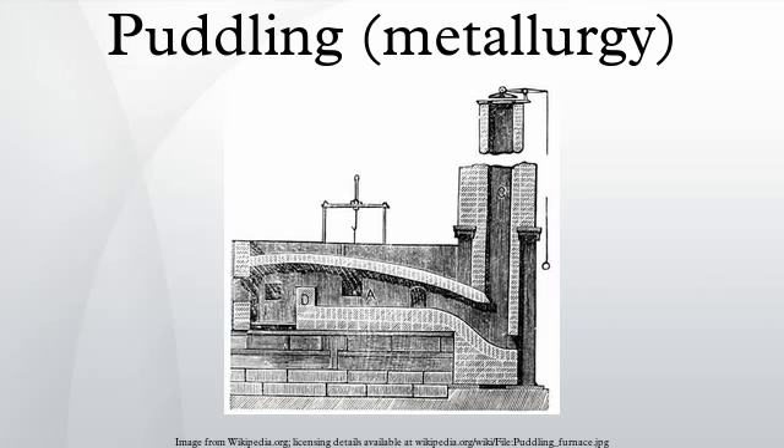When the iron came to nature — that is, to a pasty consistency — it was gathered into a puddled ball, shingled, and rolled. This application of the rolling mill was also Cort's invention. Ninety years after Cort's invention, an American labor newspaper recalled the advantages of his system: when iron is simply melted and run into any mold, its texture is granular and it is so brittle as to be quite unreliable for any use requiring much tensile strength. The process of puddling consisted in stirring the molten iron, and had the effect of changing its atomic arrangement so as to render the process of rolling more efficacious. Cort's process only worked for white cast iron, not gray cast iron, which was the usual feedstock for forges of the period.